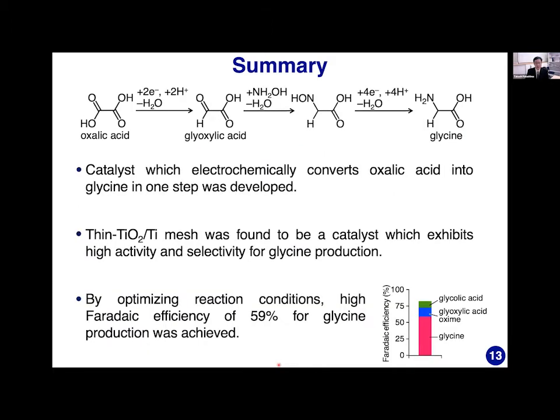Now let me summarize my talk. A catalyst which electrochemically converts oxalic acid into glycine in one step was developed. Thin titanium oxide titanium mesh was found to be a catalyst which exhibits high activity and selectivity for glycine production. By optimizing reaction conditions, a high Faraday efficiency of 59% for glycine production was achieved.